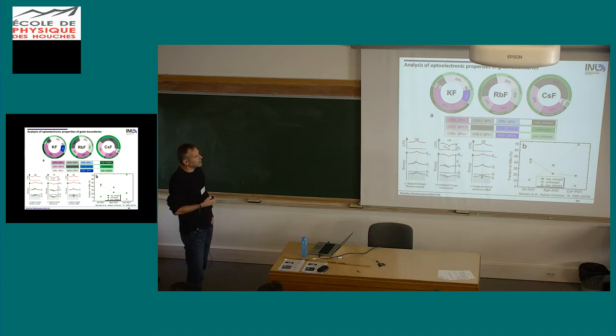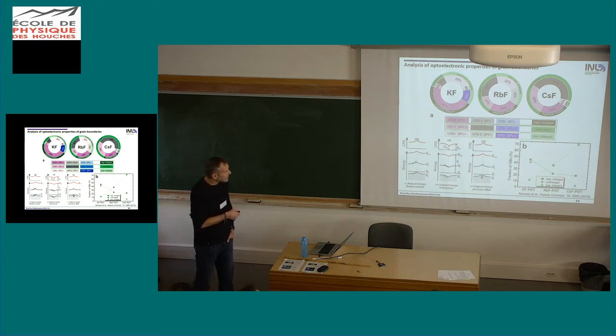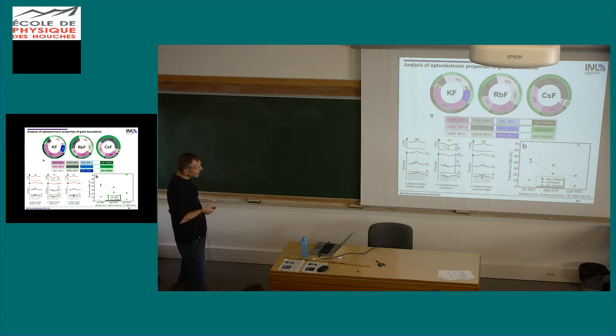Then we looked at what happens if we illuminate the sample, and we can analyze this according to different situations. If the CPD goes up, the surface photovoltage could be down, which means we get a lowering of this upwards band bending, but there could also be no surface photovoltage or an upwards surface photovoltage, which would mean that the barrier gets higher under illumination. We analyzed all of these cases, and in a pure band-bending situation, in this case, for example, we would have positive charges sitting at the grain boundary, and then under illumination, the band bending would reduce because these fixed positive charges would be shielded. So in this case, we have positive trapped charge.